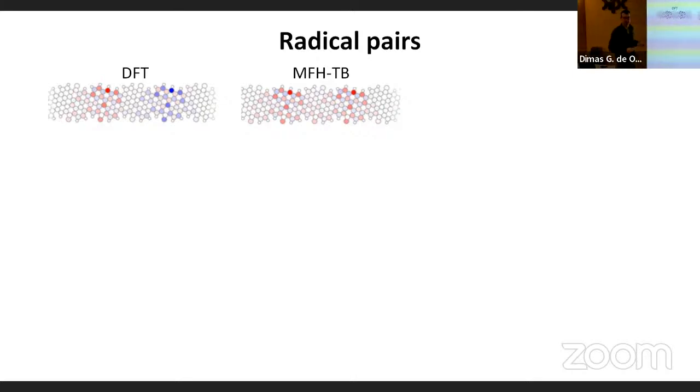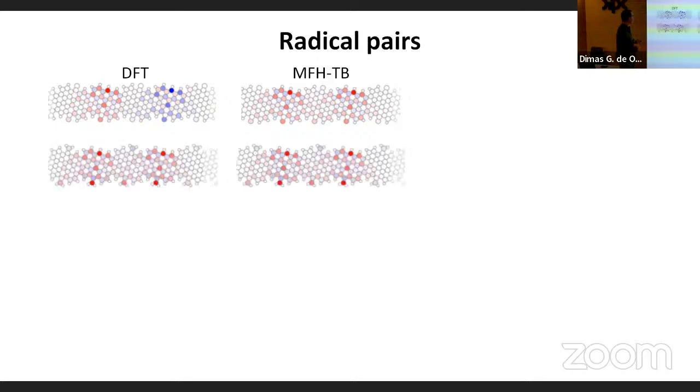And then what we thought is, okay, let's make a counter experiment, a theoretical experiment, and calculate how the alignment of these spins would be if we have a situation that is really more similar to this tight binding case. So you just add another electron, but on a carbon atom. So you add basically a CH2 group at these positions instead of the ketones. And then it would be just like the ketones, you would have a double bond between these two carbon atoms. So the conjugation pattern as you draw it would be similar.